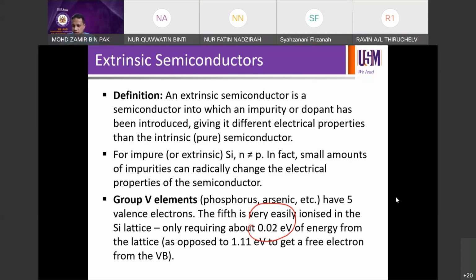So they will introduce defects due to the incorporation of dopants. They're electrically active. They will affect later on the process that we call recombination. They will induce recombination that we're going to learn later on when we talk about generation and recombination of carriers. So they will become defects, and you don't want this to happen after all.